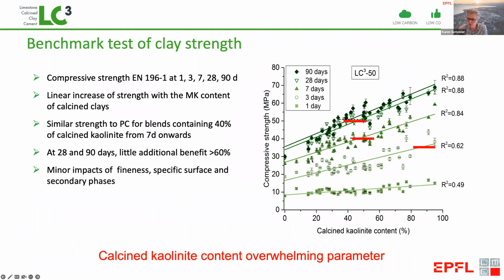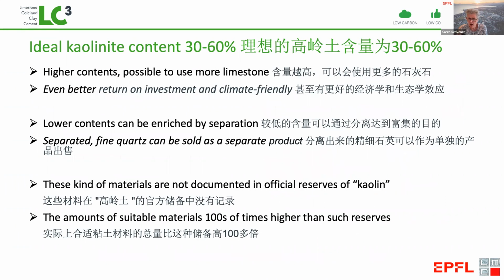And we can see in terms of strength development that the red lines indicate the reference strength of the pure Portland cement. So at, say, 7 days, you can get the same strength of the Portland cement with a kaolinite content around 30 to 50%. If you have higher contents, well, you can just dilute it with more limestone. Even lower contents can work out well because you can enrich them by separation.